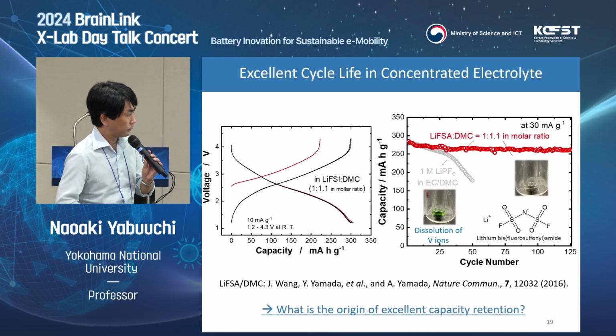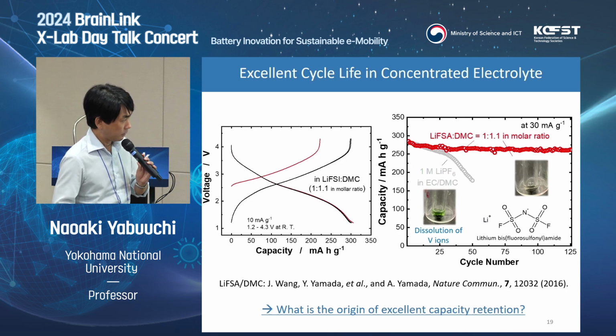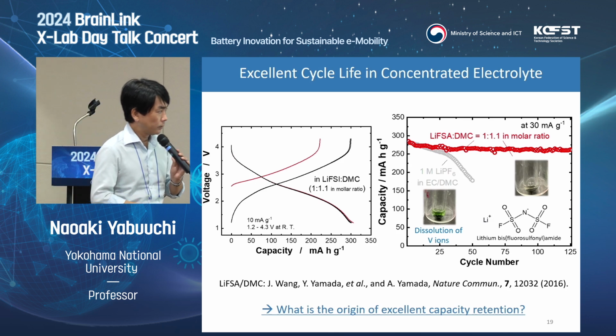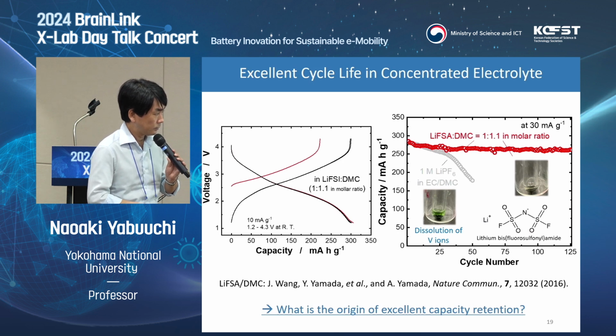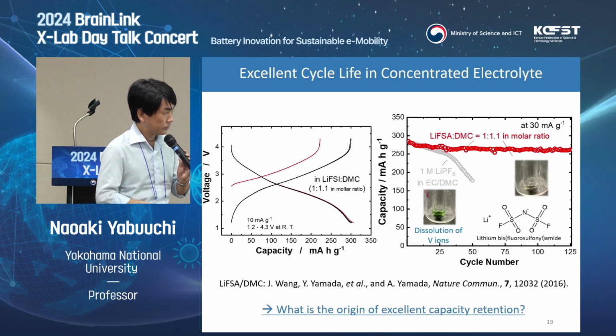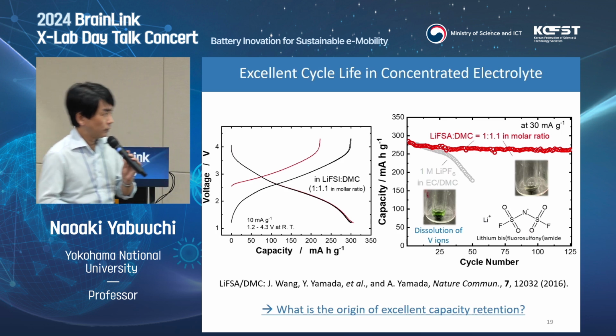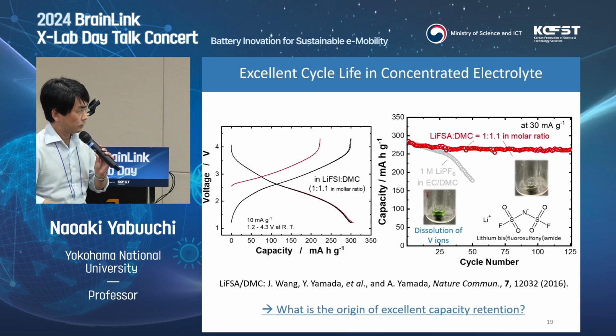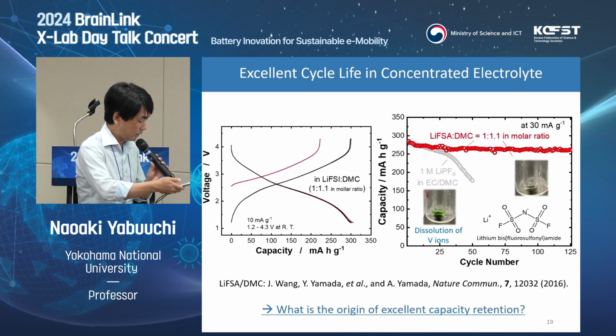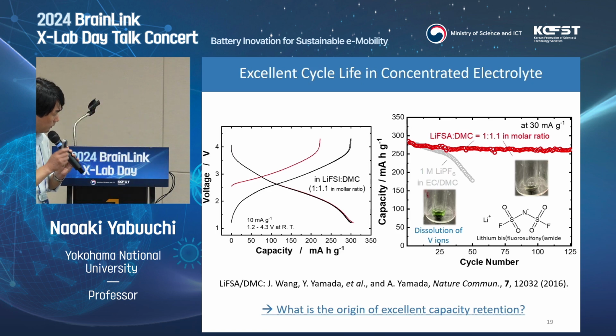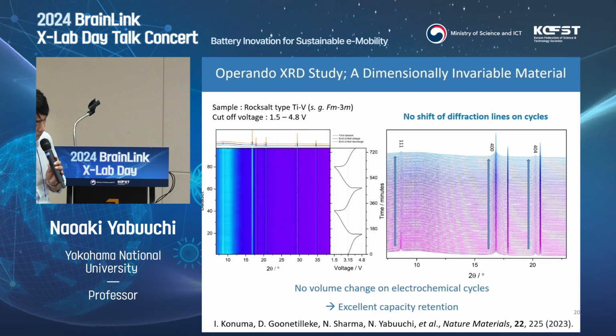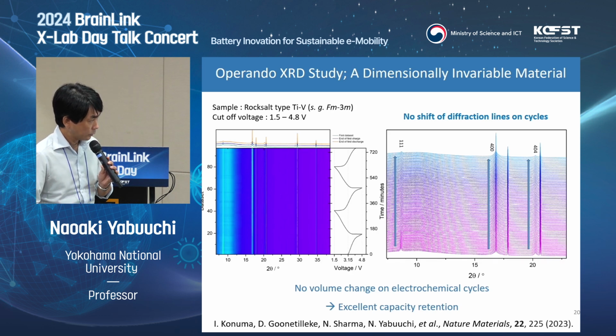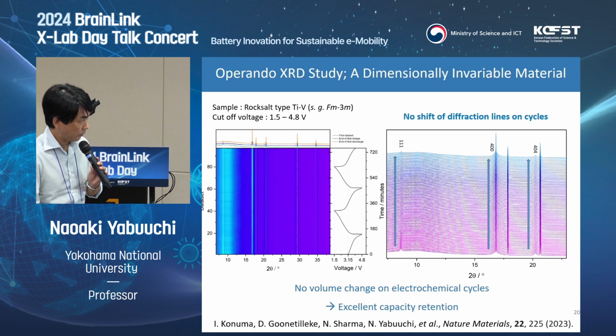So this is after a storage test with a conventional electrolyte and also concentrated electrolyte solution at 50 degrees Celsius for 2 days. Now, the yellow coloration is clear evidence of vanadium dissolution with conventional electrolyte solution. But you cannot observe any evidence of dissolution of vanadium ions for highly concentrated electrolyte solution, leading to good reversible capacity and good capacity retentions. However, an important point is that this sample has a very unique phase transition process. Volume change cannot be observed. Diffraction line position is always the same.